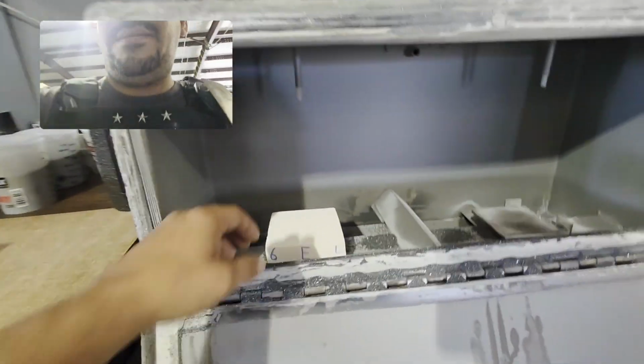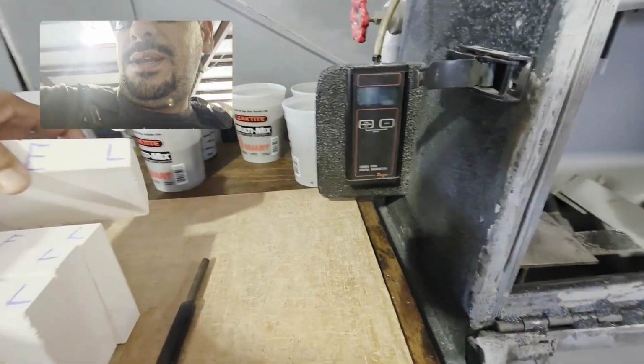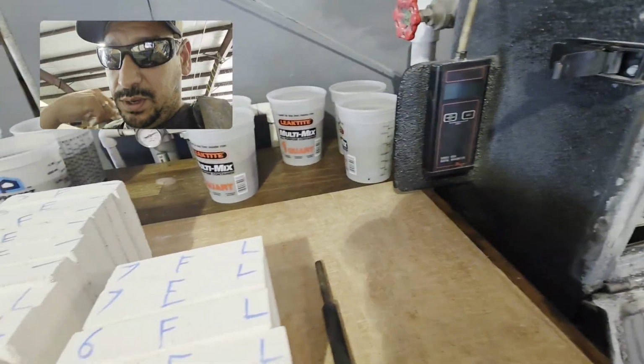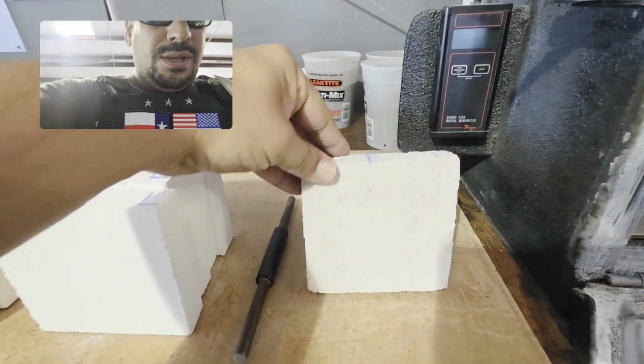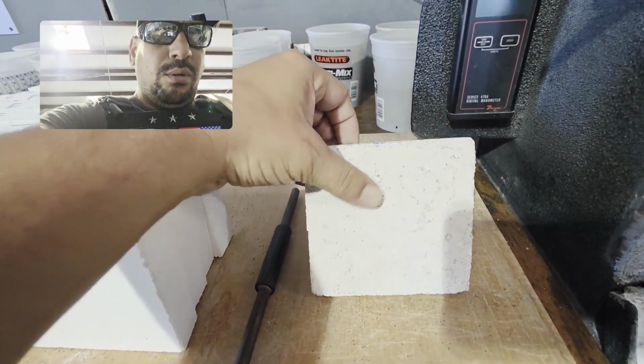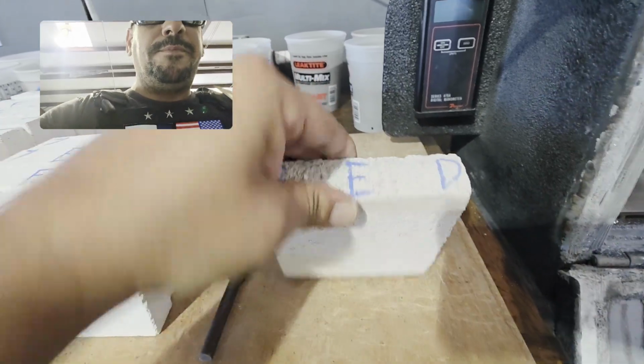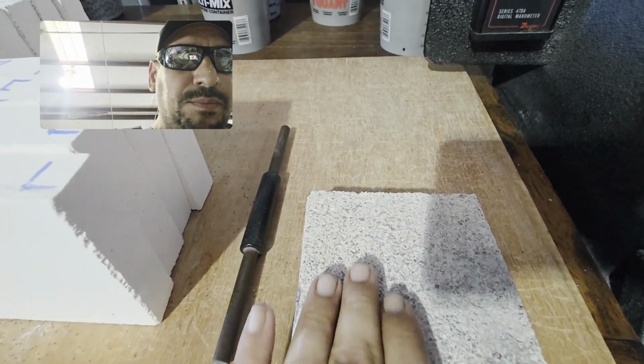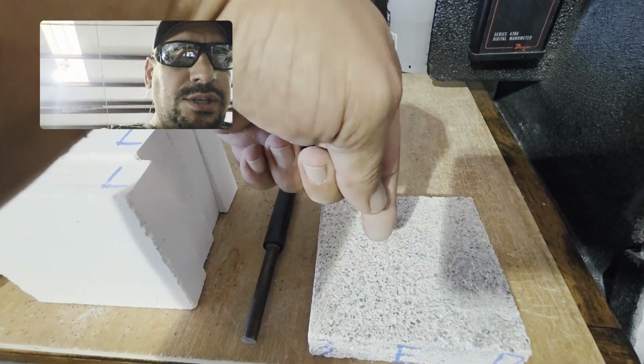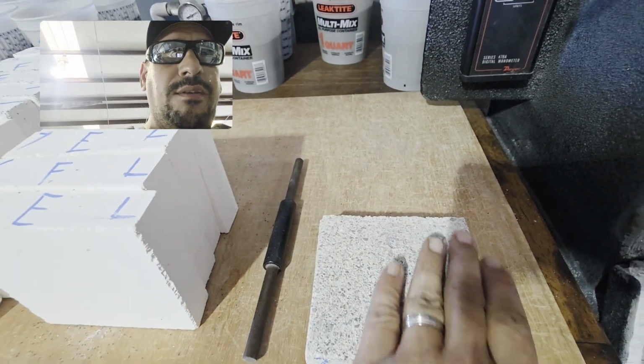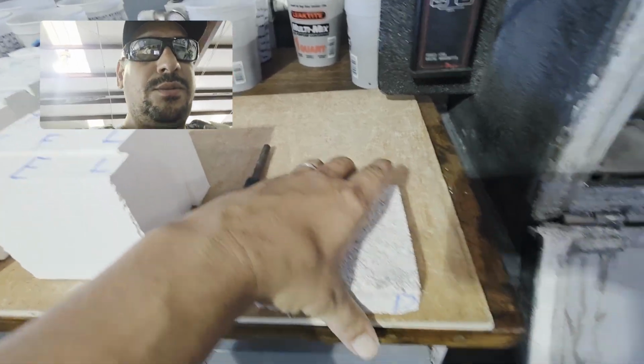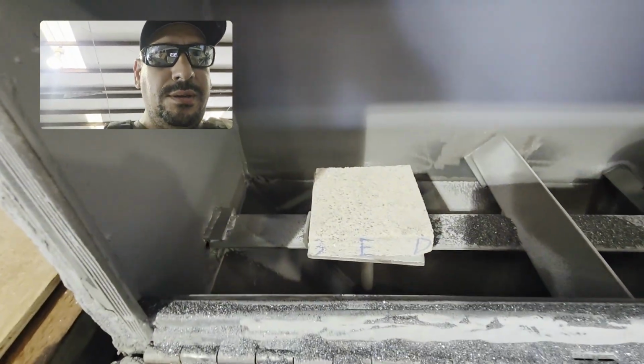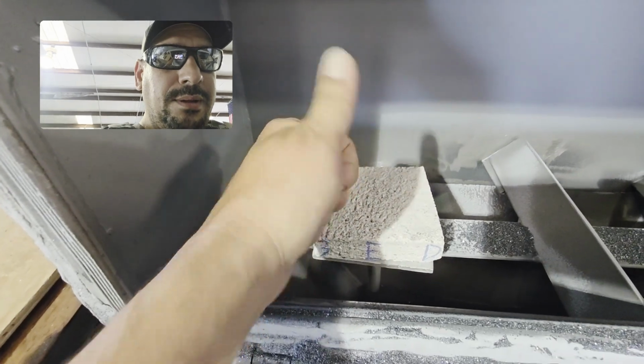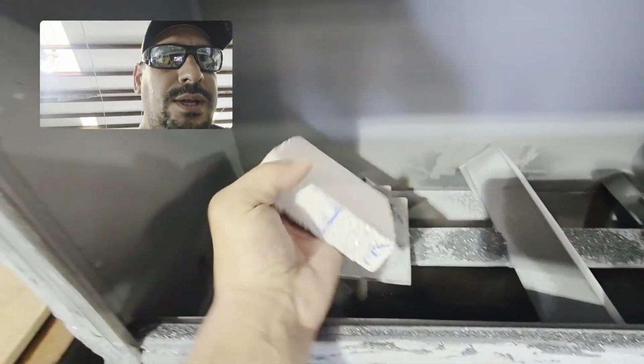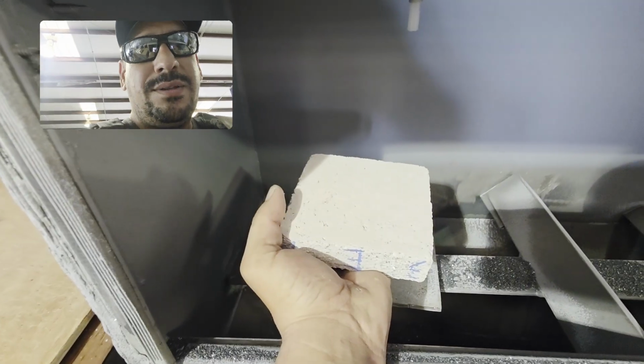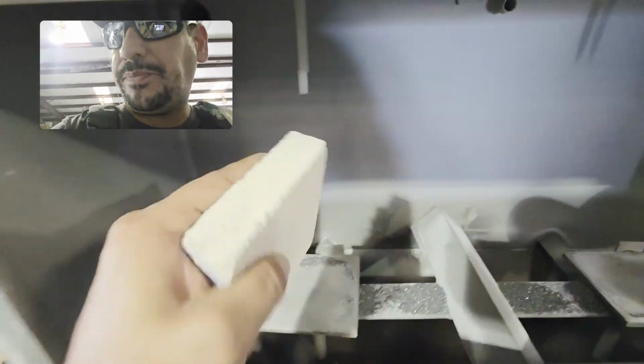You have a tolerance of like an 1/8 inch or so. And then the plate that is abraded, the surface of it, which you can't really see on that specimen because it's white. So you can see here on the back side where this was the mold bottom or the mold side. Then on top, you can see where it's been cut. So it's this direction because this is the most representative of the hot face. That's another test question. So it needs to go into the machine with the hot face facing up and not the other way. Doing it this way will give a false reading, a false number.